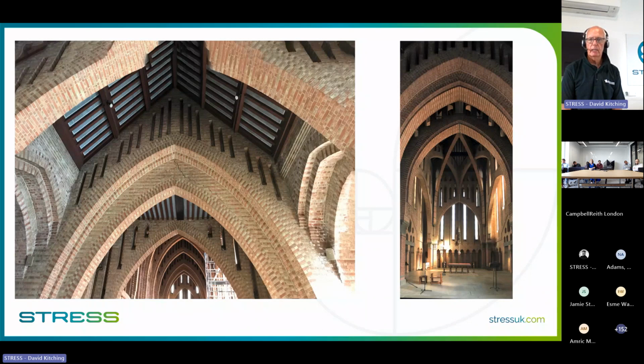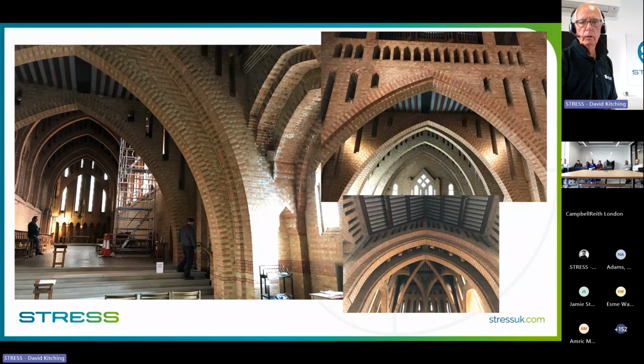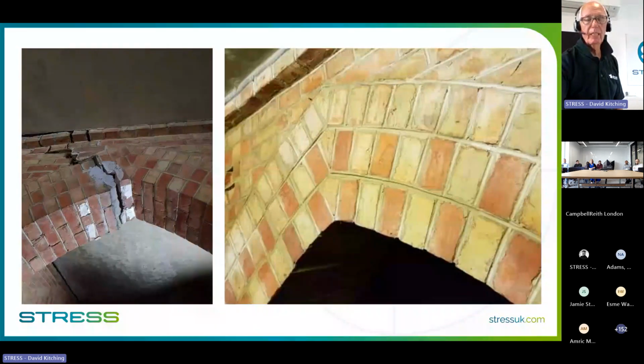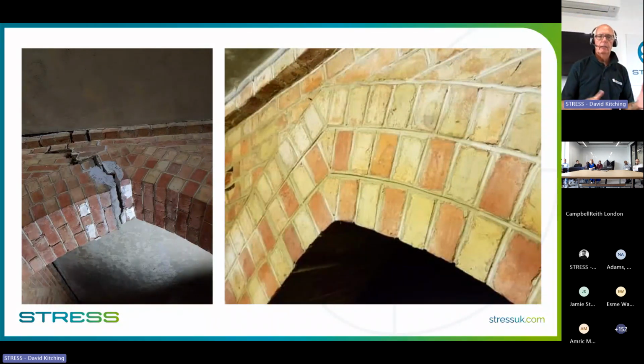So we were asked to go and analyze it, have a look at it, see what we could do. And we came up with a series of plates and masonry reinforcement to ensure that the brickwork stayed where it was. Stunning. 12-meter tall towers. We couldn't put full scaffold up because it would have stopped use of the main aisle, and so we had to work off tall scaffolds. But you can even see in the crypt downstairs the sorts of damage that we were finding. And so what we needed to do in some circumstances was do a little bit of rebuild of the arch, but we incorporated masonry reinforcement into it to ensure that it could crack if it needed to, but nothing would fall out.